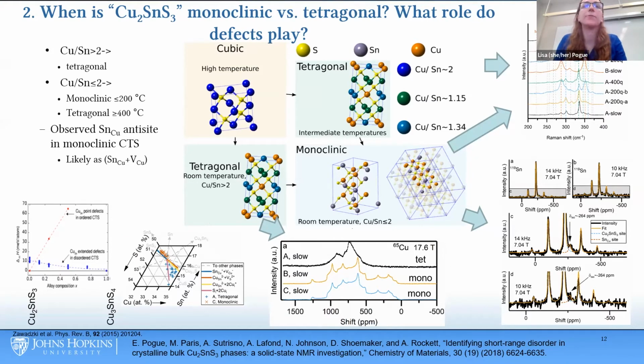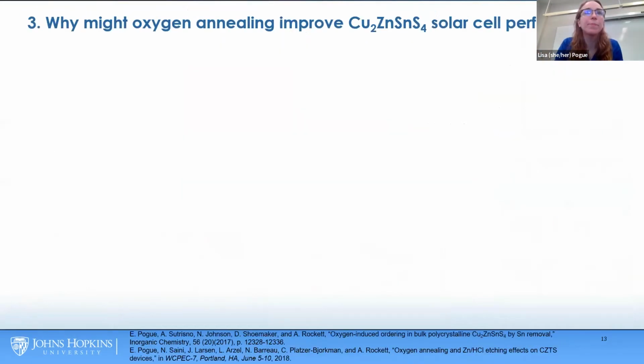Also, interestingly enough, I was able to use solid state NMR to directly observe a tin on copper antisite defect in the monoclinic phase, which was unique because we're directly seeing a point defect there. And so it points a way to better study the effect of defects in those devices.